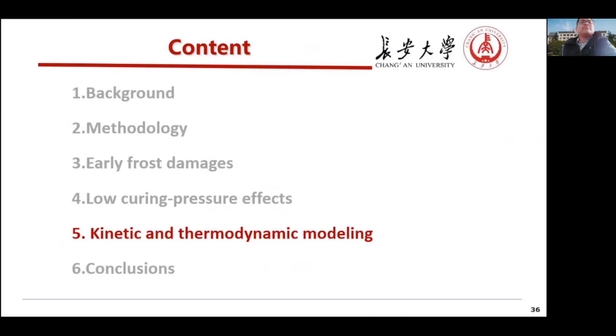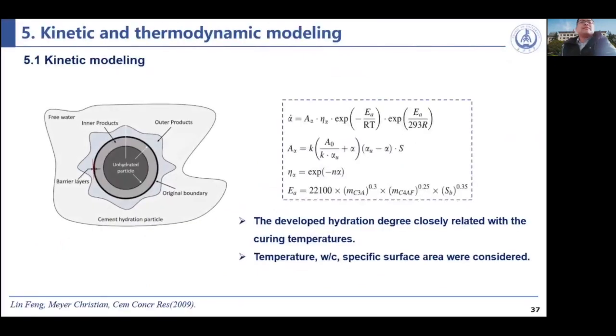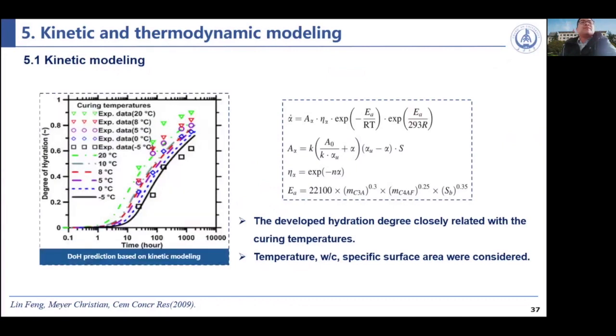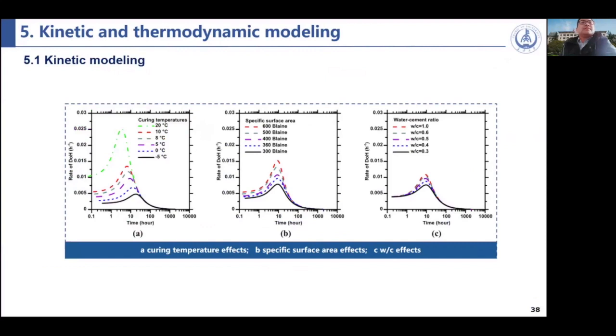We also did some modeling. First, we did some modeling to calculate the cement hydration under the lower temperatures and the lower curing pressure. The developed hydration degree is closely related with the curing temperature, and in the modeling we considered the curing temperature, the water cement ratio, and the specific surface area, and we also included the lower curing pressure. This is some data and the results we got in the simulation and modeling.